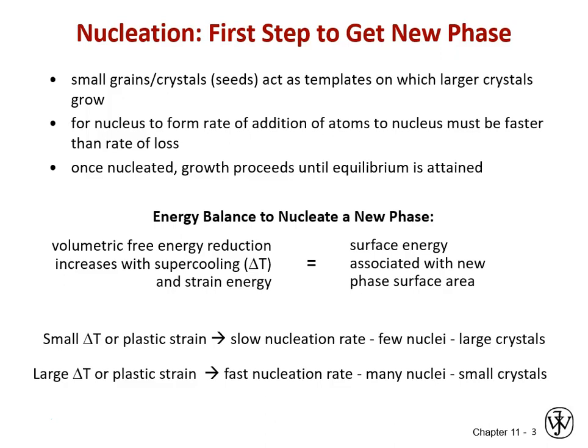So greater drive means greater amount of material affected per unit drive. On the flip side, though, every time we form a new phase, we're forming a new surface. And as we discussed back in our defects section, these 2D surfaces have a higher energy just because everything isn't all in its perfect crystalline orientation and equilibrium spacing. So we're decreasing the energy per unit volume by forming the new phase, but we're increasing the overall surface energy of the material by making a new surface.